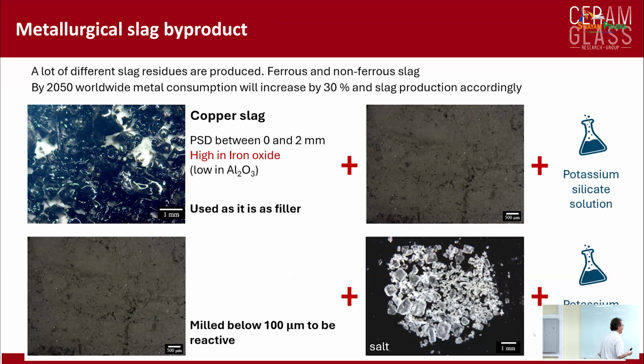And speaking of waste, one possibility is to use metallurgical slag. Of course, you can use slag from the steel industry, or you can use slag from other metallurgical works. And we had a project for using copper slag, which is basically based on iron oxide. And being a slag, of course, it's amorphous because it's extracted from the reactor and cooled quickly, discarded, cooled quickly.